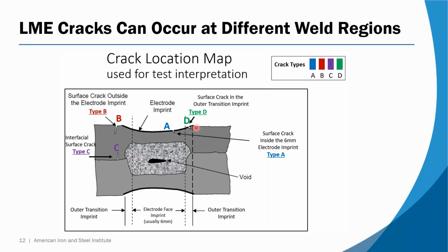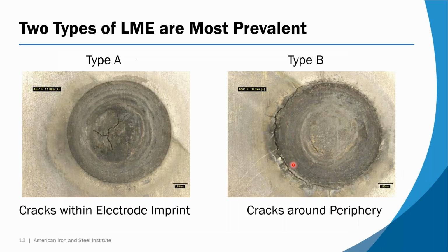Type D is in that no man's land between the electrode face and the undisturbed original surface. So it's that region that only touches the electrode during the act of indentation. Okay, so A, B, C, D. Now, the 2 cracks that are most prevalent in this spot weld test ended up being type A and type B. Type A, you can see it's under the electrode. Type B is peripheral.